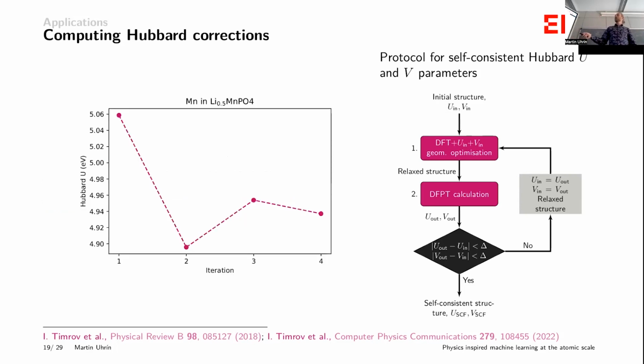So a typical calculation for U might look like this, where you do several iterations until you say, okay, you know what, from here to here, the U value in this case didn't change much. So we're now self-consistent. The U and the energy and the structure are all consistent with each other. So here, if you're doing 4, you know, that's going to be an 80 times cost. And typically you might even do more, 5. So you're paying 100 times the cost of a normal calculation.